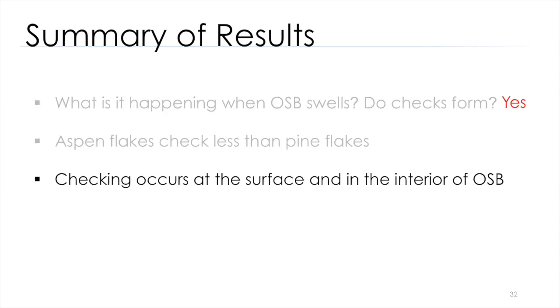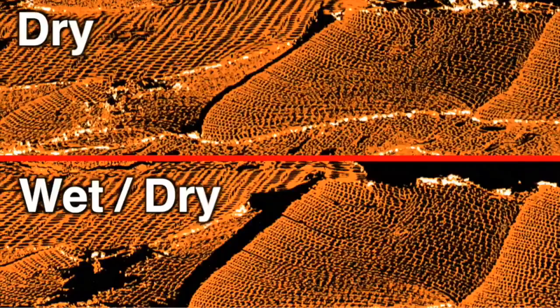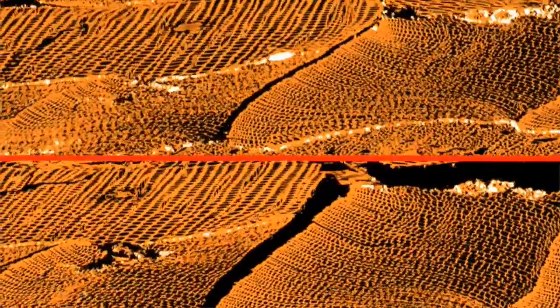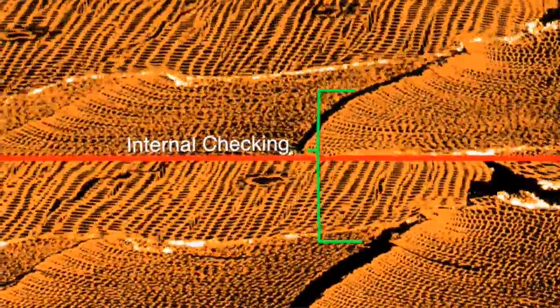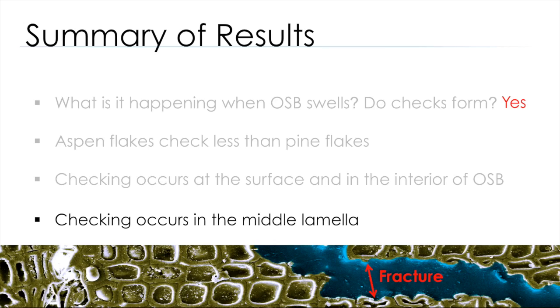Checking occurred on the surface and also deeper in the OSB, as you can see from the CT animation from the cross-section of OSB, before and after swelling at the same location from the datasets. So we can see that the checks go through the OSB and they get bigger after swelling. So as we saw previously, it's occurring mainly in the middle lamella.